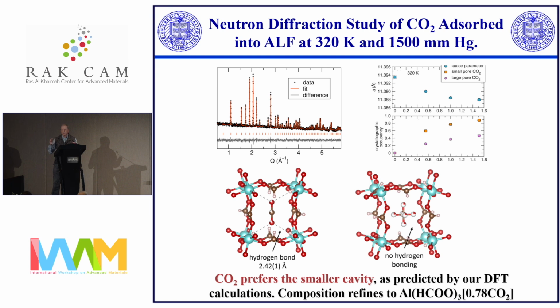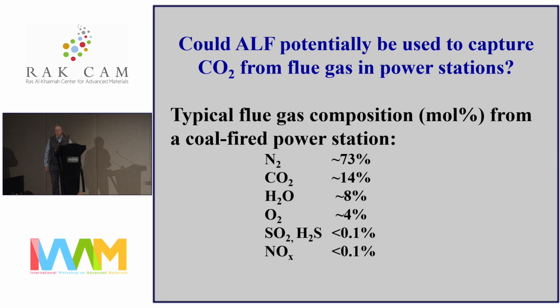And then the other cavity is slightly larger, and when we reabsorb CO2, the CO2 goes in there, and we followed it in real time as we were dosing. They have beautiful equipment, so we can dose it in real time and follow the uptake and the population in the two different cavities and so on. So if we could fill all of both cavities, the composition would be down at the bottom there, aluminum formate 3 times with 1.0 CO2. As it is, we don't quite fill all of the cavities up at 1 atmosphere, so it comes to be about 78% filled of CO2.